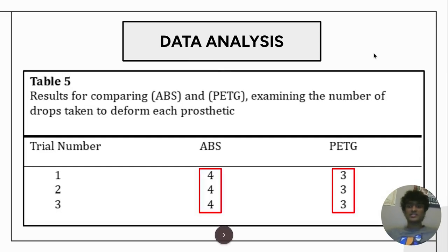The next tests that were conducted had results that were non-normal. For example, a standard deviation of 0 was achieved here, and that's why an independent samples t-test was not able to run. The number of drops was measured here to see how long it took to deform each prosthetic. For ABS, for each trial, it took 4 drops. For PETG, for each trial, it took 3 drops, showing that ABS on average survived longer than PETG did.